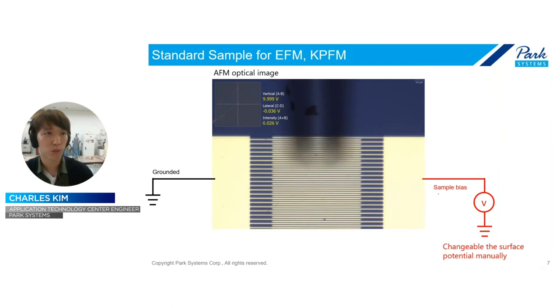So this is the sample, for which I will show you the live demo for the EFM and the KPFM. This sample has two different electrical patterns. The left-hand side is electrically grounded, and the right-hand side is connected to the AFM sample bias line. That means if I apply any kind of sample bias here, then I can change the surface potential manually. After that, if I scan in here, then you can see the zero grounded electrical property, and on the other hand, you can see the different potential which you apply to the sample bias at the same time. So let me show you the real measurement.